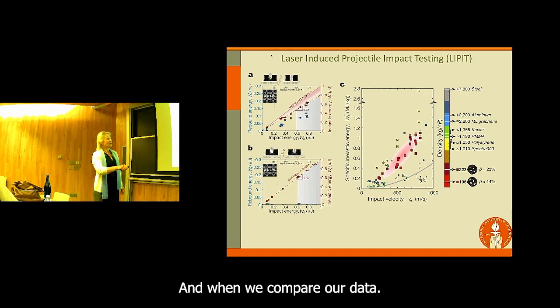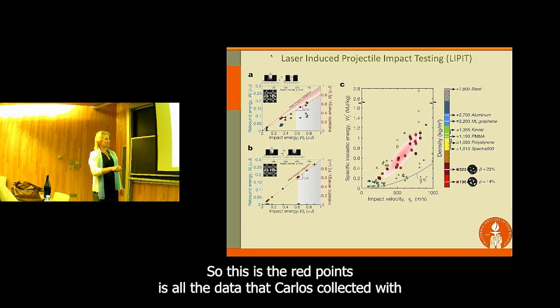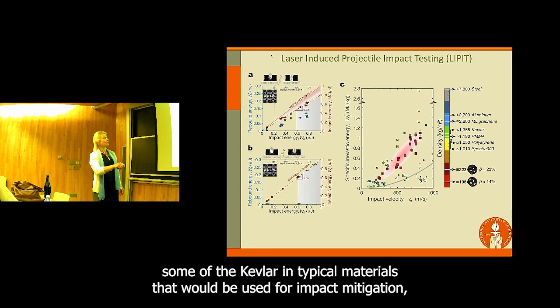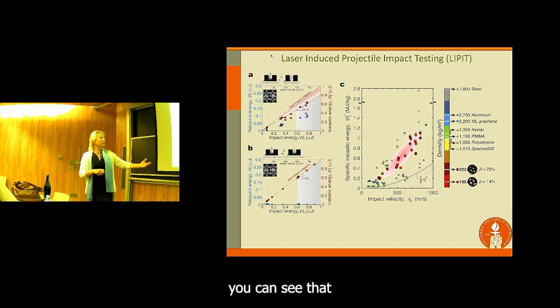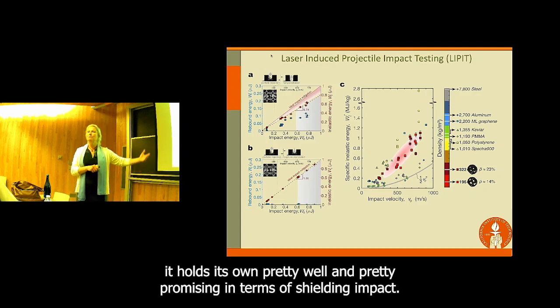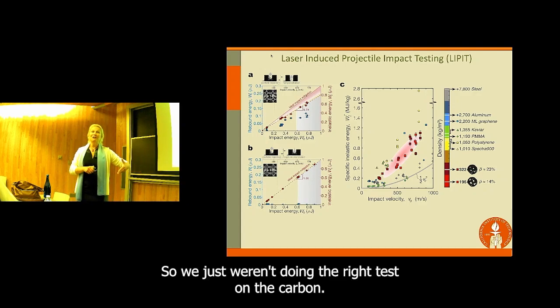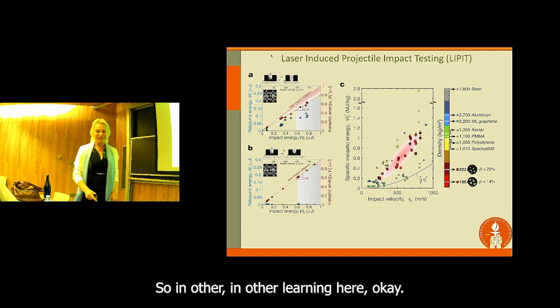And when we compare our data, the red points are all the data that Carlos collected, with some of the Kevlar and typical materials that would be used for impact mitigation. You can see that it holds its own pretty well and is pretty promising in terms of shielding impact. So we just weren't doing the right test on the carbon. So that's yet another learning here.